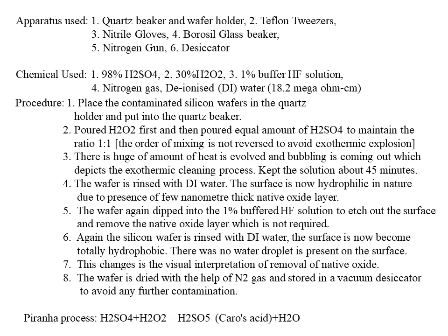So we pour the 1% buffered HF again, then take the wafer out of the solution, and again rinse with DI water. But remarkably, for the second cleaning, we have clearly shown that no water got stuck over the silicon wafer surface.